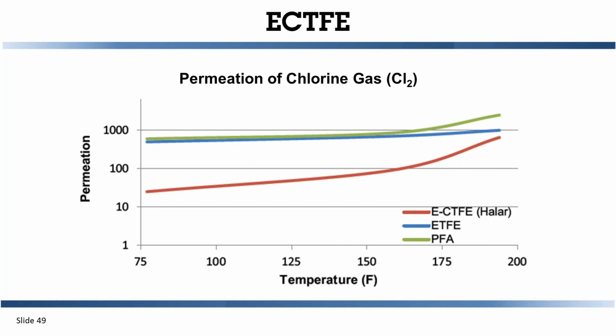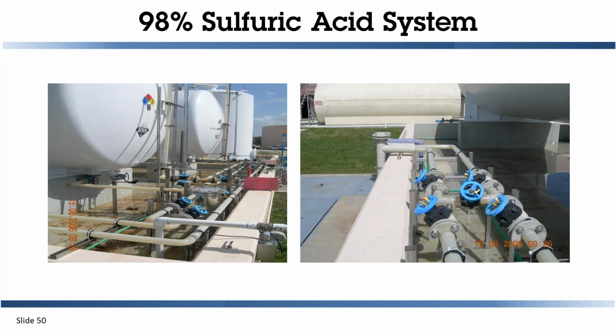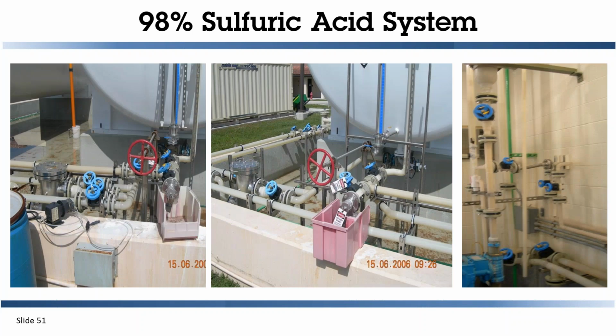Compare that with PFA, another fluoropolymer that's readily available. We have a log scale on the left, and we have a great reduction in that permeability. So that long-term permeability will greatly increase the lifetime of ECTFE. Couple applications, wastewater treatment plants that are using 98.3% sulfuric acid. Lots of tanks taking this into a building for the dosing.